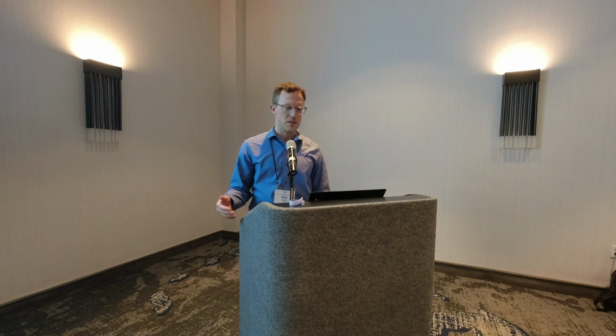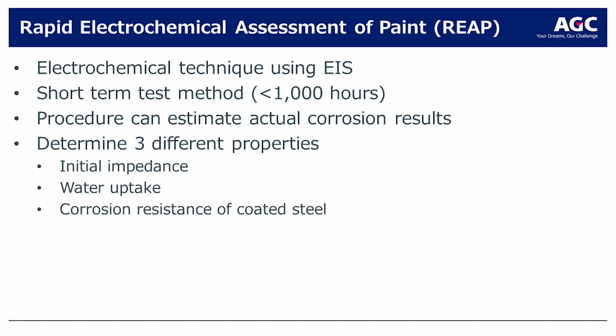So just to highlight some of the takeaways, we looked at the EIS testing. It's a short-term test method, meaning it takes less than 1,000 hours, so we can get quick information back, and you can get actual corrosion results that determine initial impedance, the water uptake, and the corrosion resistance of coated steel.